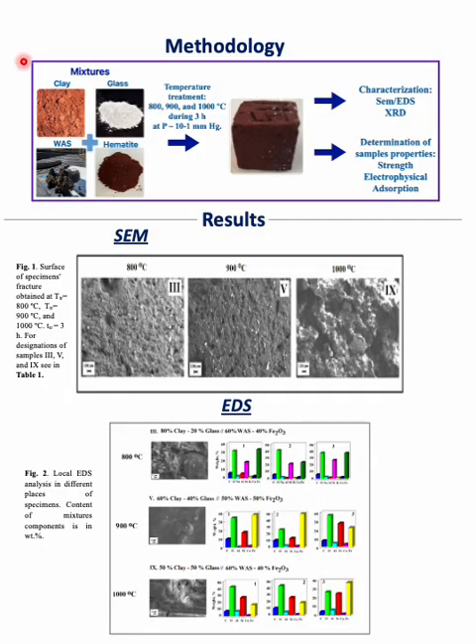The methodology consists in preparation of 3D specimens from homogeneous mixtures of clay, glass, waste, and hematite. After the temperature treatment of the specimens at 800 degrees Celsius, 900 degrees Celsius, and 1000 degrees Celsius during 3 hours under conditions of oxygen deficit, the specimens were characterized by SEM, EDS, X-ray data, and determination of sample properties: strength, electrophysical, and adsorption properties.